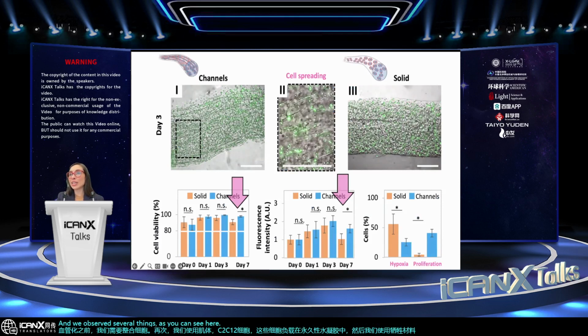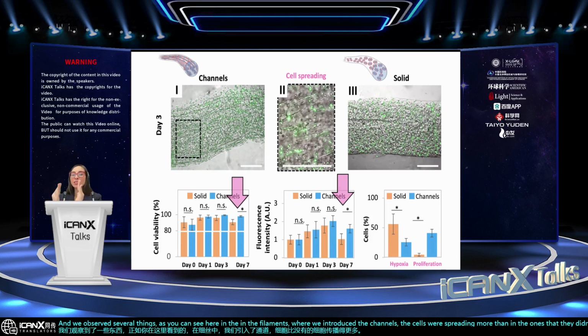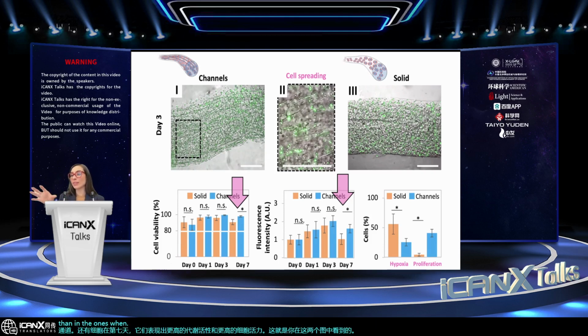In the filaments where we introduced the channels, the cells were spreading more than in the ones that didn't have channels. And also the cells at day 7 exhibited a higher metabolic activity and higher cell viability. This is what you can see in these two graphs, in the filaments with channels than in the solid filaments.